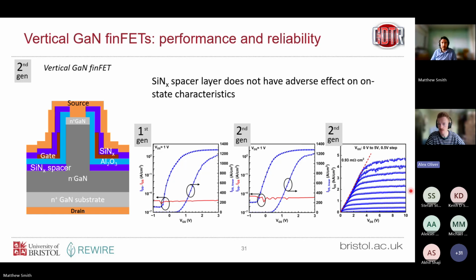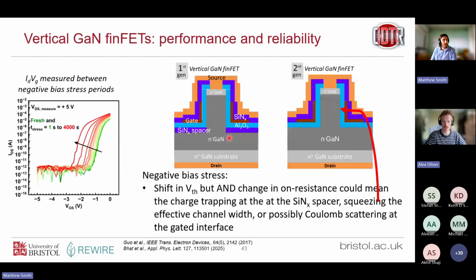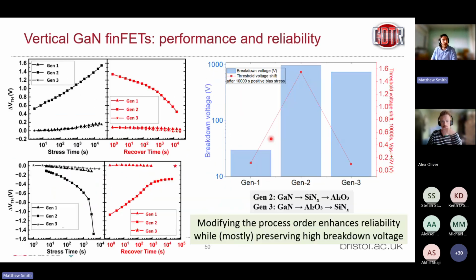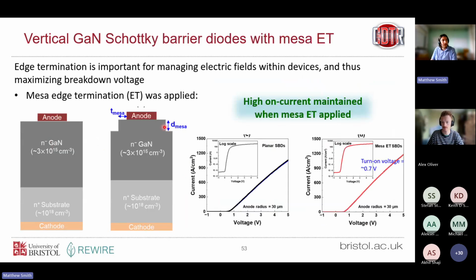Great. I think final question. So it's from Abdul Fatai. How sensitive is the BV to the MESA sidewall angle, and where does the BV actually initiate? So the MESA edge or the bulk GaN? Yes, again, I think I sort of covered that one in response to an earlier question, but it is sensitive to the sidewall angle. It's also going to be sensitive to the rounding at the base of the MESA here. So depending on the conditions, if we have a very small T MESA, then actually we start to see a peak in this region in simulation. But actually smoothing that corner out is very common practice using a wet etch after a dry etch fabrication process. So all of these things, little tweaks to these designs we can do to have measurable and significant impacts on breakdown voltage. So maybe we can follow up if we're looking for some specific numbers there. But yeah, thanks for the question.